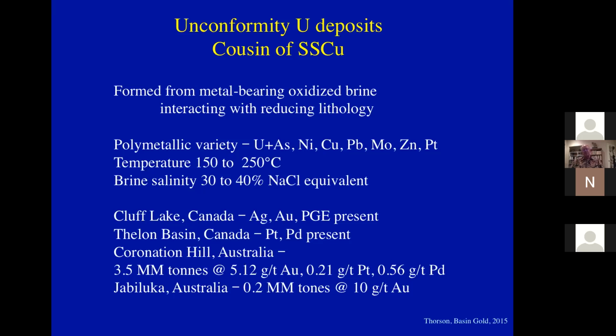In the Thelon Basin, which is a similar basin in Canada, there are both platinum and palladium present. At Coronation Hill in the Alligator River part of Australia, there are very high grades of precious metals in small unconformity uranium deposits. Coronation Hill had 5 grams of gold, 2/10 of a gram of platinum, 1/2 gram of palladium. Jabiluka was even, although smaller, much higher grade with 10 grams of gold in these uranium ores.